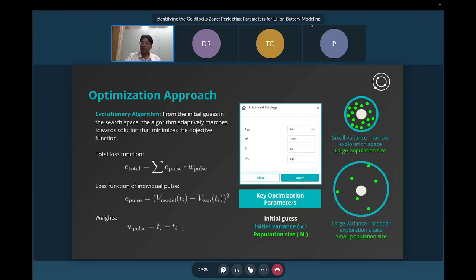More initial guesses means more runs it will undergo, thus increasing the optimization time. At the same time, if you have a larger variance, what I'm trying to say is that you have an initial guess over here, and if you give a larger variance, this is the set within which, if you consider this as an n-dimensional hyperspace of these parameters, this is the space within which it will start trying these initial guesses. And depending on the number of guesses that you want to start with, it will have that many random guesses within this zone. And if you reduce this variance, then it is going to try values very close to the initial guess. And if you increase the number of initial guesses, then it will have a much denser population within that bound.